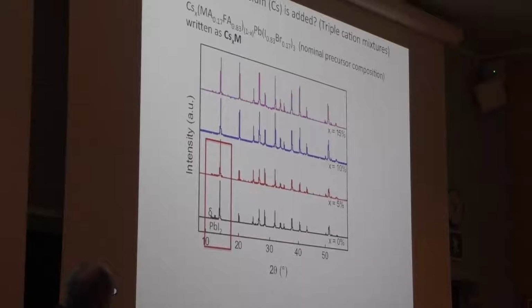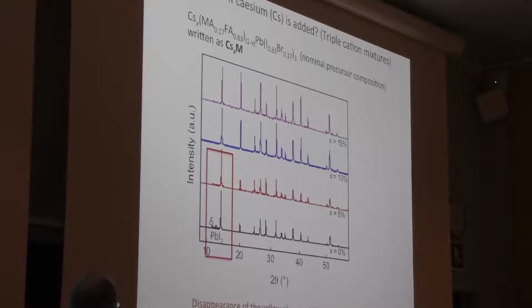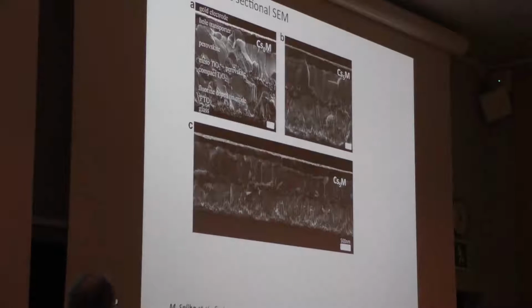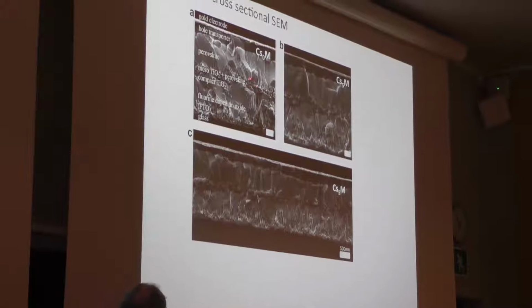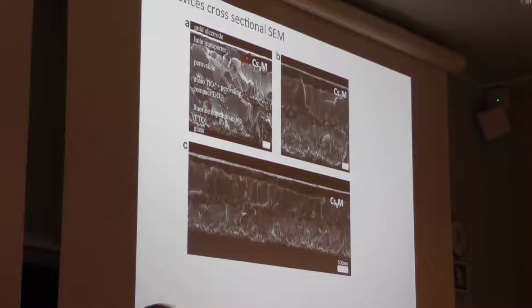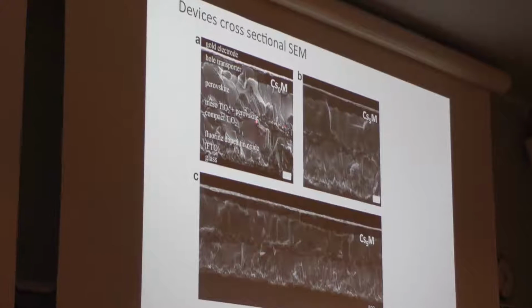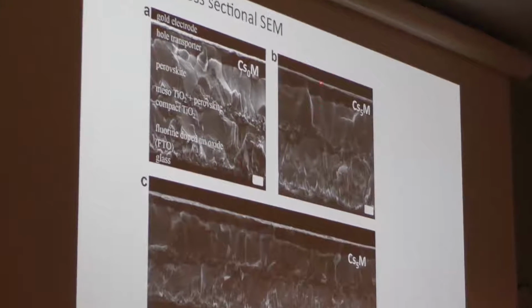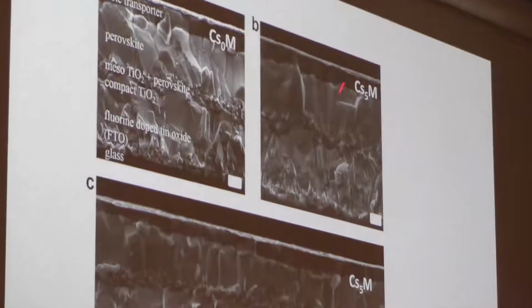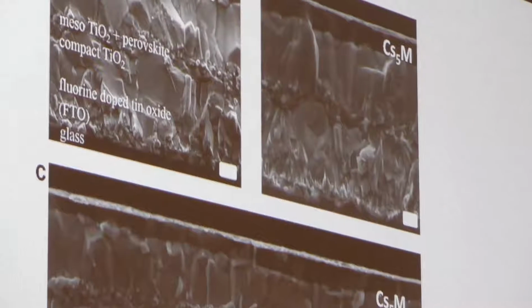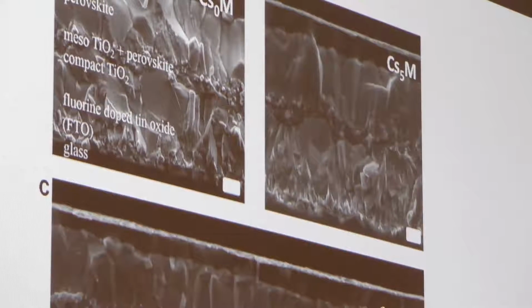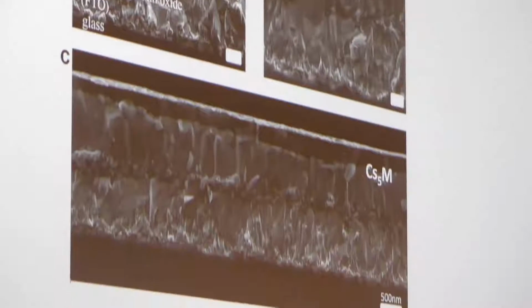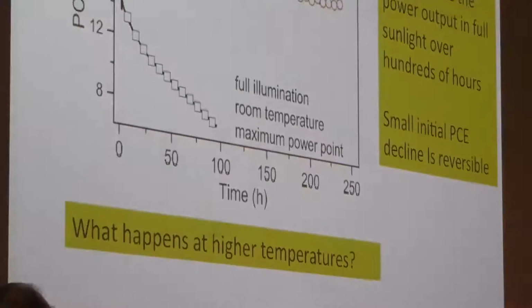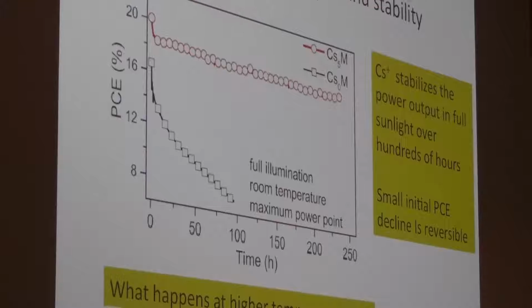And at higher concentration of cesium it's the same. So this is our standard protocol, I would say, at the moment. We can see here that without the cesium, well, it's not bad, it's good, the crystals, but with the cesium 5%, really columnar structures all the way through the compact layer. So again, larger crystals, higher quality films, and that also increases the efficiency and, more importantly, stability.